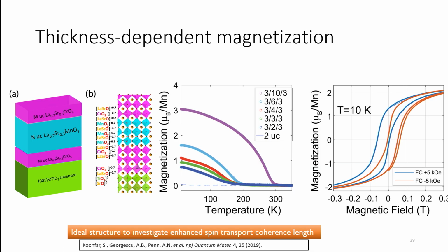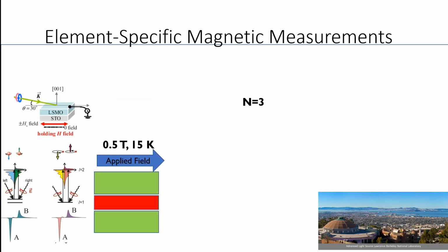We can also change the thickness of the LSMO and keep the spacer layer thickness fixed. But we found that as we change this LSMO thickness and measure the magnetization, the magnetization per manganese increased, and the transition temperature went towards room temperature as we increased the LSMO thickness. So what that tells us is that there's something else which might be happening here, which we're not accounting for in our very simple model. In our simple model, we assumed that the lanthanum strontium chromate was antiferromagnetic, so all the spins would cancel out and there would be no contribution to the total magnetic moment.